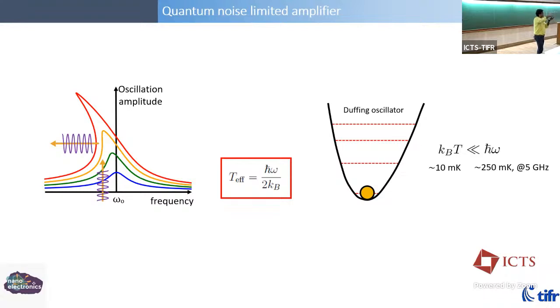If it gets cleaved off, then you put it back and then finish measuring, and after the measurements are over for a while, then we do the AFM. So we don't have very deterministic control to say, okay, I make the upper layer 10, lower one 5. Right now we are not at that stage to deterministically make different thicknesses. So far, in what experiments we have done, we don't see any thickness dependence. It's just the interfacial Josephson junction. So zeroth order, it doesn't care about the thickness of the superconductor.